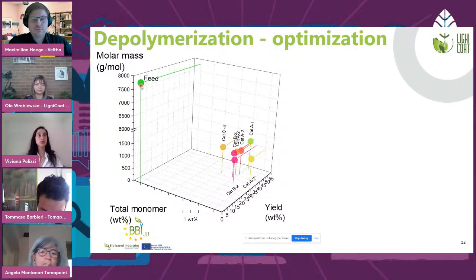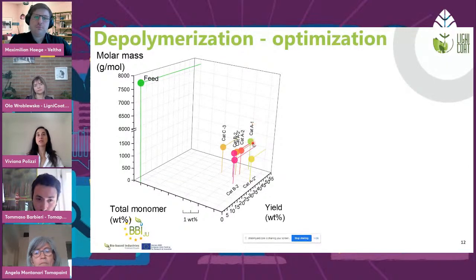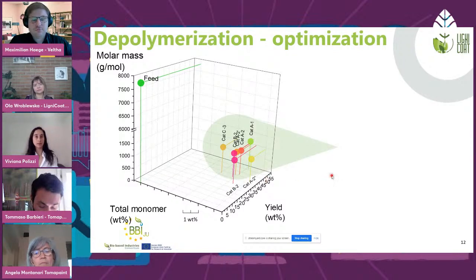So you see on the right hand side the feed, the original lignin that is characterized by a high molecular weight and a very low or zero monomer content. By applying depolymerization, we obtain, by using different catalysts, where each point is a sample, the depolymerized lignin. With different catalysts, we are able to lower the molecular weight consistently and also to produce a certain amount of monomers. Because of our analytical capabilities, we are able to characterize these samples and, for example, by